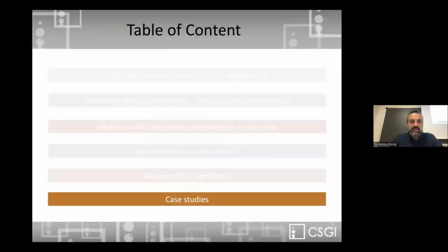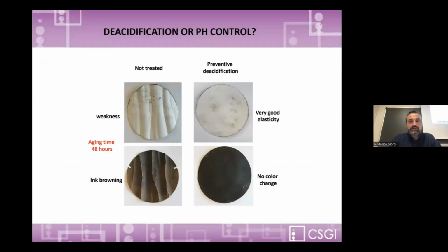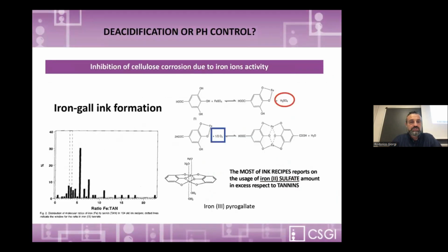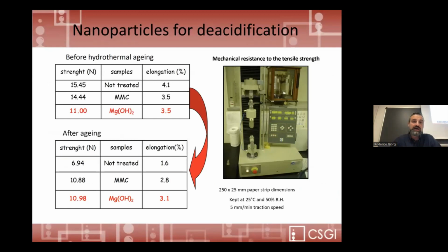As I show in the slide, we use a classic dynamometer used in the textile industry to check the mechanical resistance of a single fiber. In this case, we use a protocol that is largely used in that area, and that we modify a little because the strength involved in the process is lower than the ones they usually use. This is a classic procedure, pretty largely used, and obviously the technique is destructive, so we cannot check the benefit of the treatment on the real artworks.